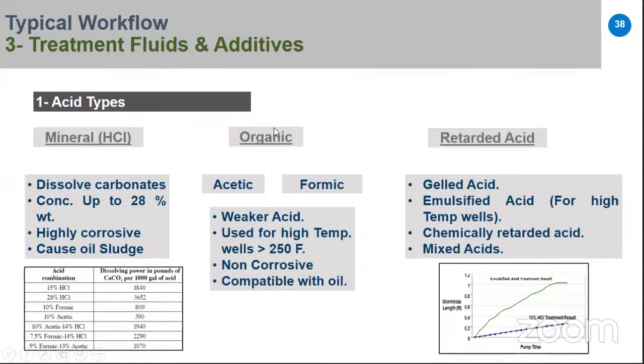Another type of acid is organic acid. We have acetic acid and formic acid. They are weaker acids compared to HCl, but they are used for high temperature wells greater than 250 Fahrenheit. They are non-corrosive, compatible with oil, and do not cause oil sludge. Finally, we have what's called retarded acid to reduce the diffusion rate of the acid. We have gelled acid by cross-linker or surfactant. We have emulsified acid, also used for high temperature wells. We have chemically retarded acid, and we also have mixed acid.